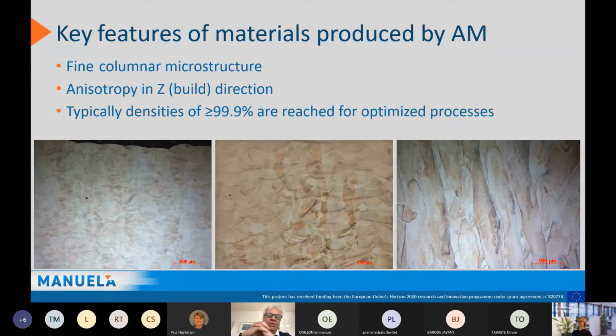So, of course, the material has to be understood from a material point of view. If I take material built in laser powder bed fusion, the microstructure becomes unique. It's not the same as a cast material or as a wrought material. There could be certain anisotropy in the build direction, but typically it's important to know that we have our process under control. We are building basically fully dense materials.